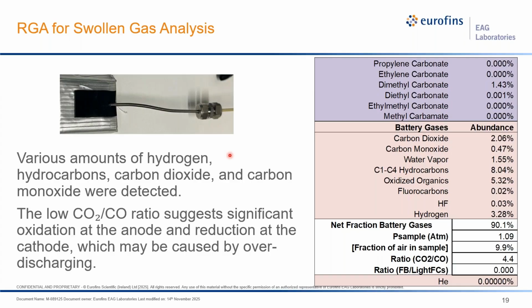And then we are looking at the CO2 to CO ratio to understand whether there is overcharge or over discharge. In this example, you can see the carbon dioxide to carbon monoxide ratio is a little bit above 4, which is pretty low. In these cases, we suspect there might be over discharging causing this battery to fail, because when there's over discharging, the oxidation step produces more carbon monoxide than the normal ratio of carbon dioxide to carbon monoxide.